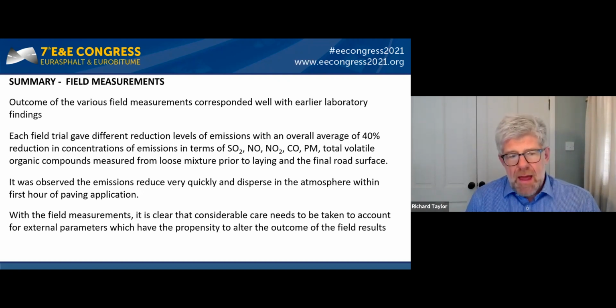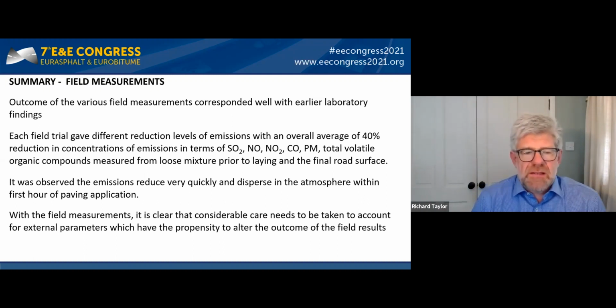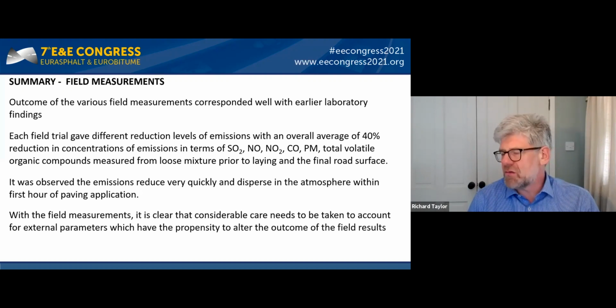in the laboratory. We would also observe during the field trials that the emissions very quickly disperse into the atmosphere. And so we try to make measurements very, very quickly when the material is fresh, when it's just being delivered to the paver. If you hang around and try to make measurements later, maybe from a stationary device, you're not going to pick up a lot of emissions. And of course, I've said it already, but you really have to take considerable care with the external parameters, upwind measurements, downwind measurements, etc.